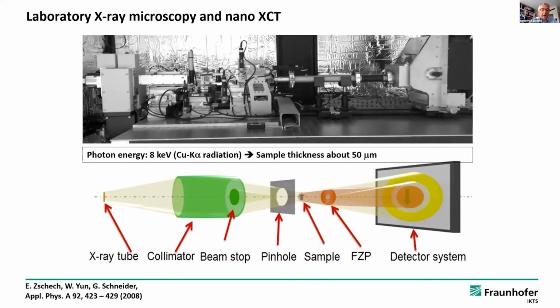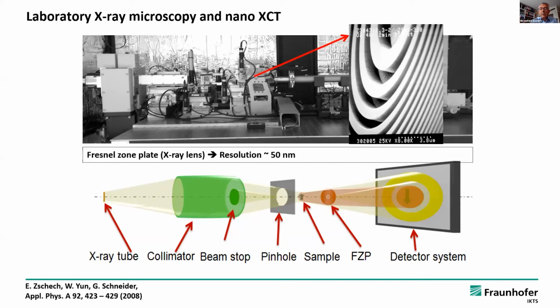Now here you can see how a laboratory X-ray microscope looks like. Generally, it looks very similar, from the scheme, to an optical microscope. However, you need an X-ray source and you need also other optics, as I have told you. And for a photon energy of about 8 keV, that's K alpha radiation, you have to thin the sample to about 50 microns. I will come back to this point at the end. And you need particular focusing lenses, so-called Fresnel plates, to get a resolution of 50 nanometers. The lenses are the components that limit the resolution today.